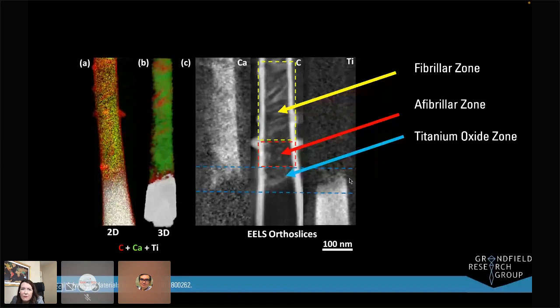What's quite interesting is we can note that there's this afibrillar zone just above the titanium dioxide and below the collagen, where we don't have collagen fibrils, but we still have a calcium signal. So we've noted this afibrillar zone at the interface. One thing that's quite hard to tell is what's happening where the titanium dioxide is. We really wanted to know, does the bone-like mineral just stop outside of the oxide layer, or is there an integration of bone all the way into the implant and into the fine features of the nano-oxide?